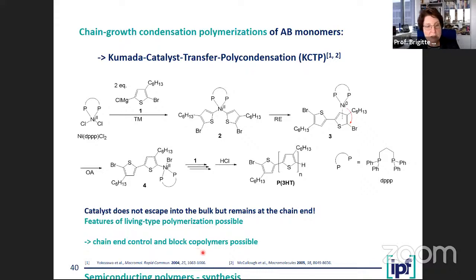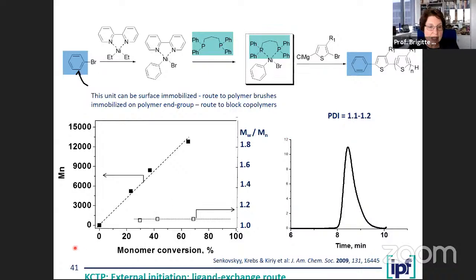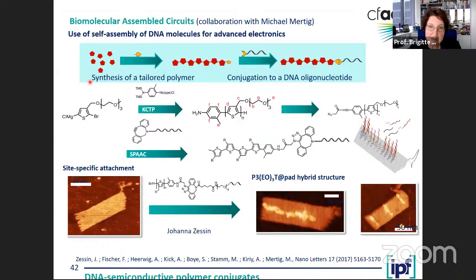Around the year 2000, by Yokozawa and McCullough, there was a new concept introduced that is chain growth condensation polymerization of AB monomers, which finally leads, for example, here to a polythiophene, which is formed by C–C coupling. But this procedure to make this polythiophene is actually following a chain growth. So you have a catalyst which is more or less sticking to the chain end, and this catalyst allows a more or less defined polymerization. And when you do it right, you can actually get a living type of polymerization where molecular weight develops linearly with the monomer conversion, and you get a nice small dispersity of the material. And you can control the end groups very well. You have a starting group, you have an end group. You can make block copolymers, for example. So that had been developed by us quite a bit in the field of functional polymers.